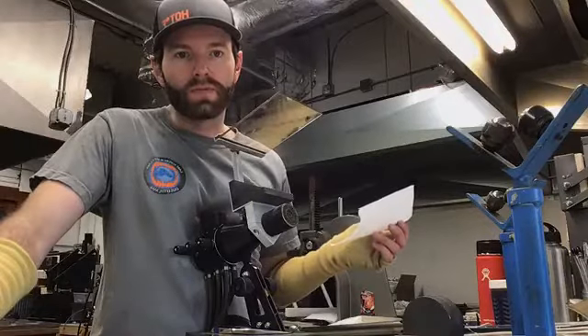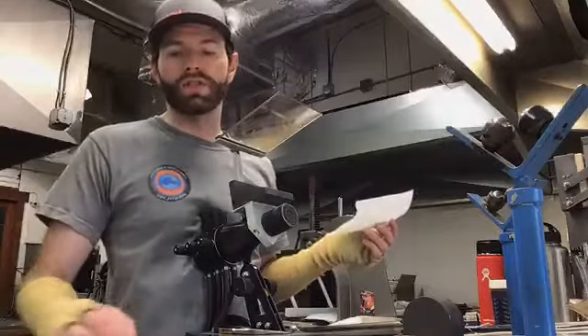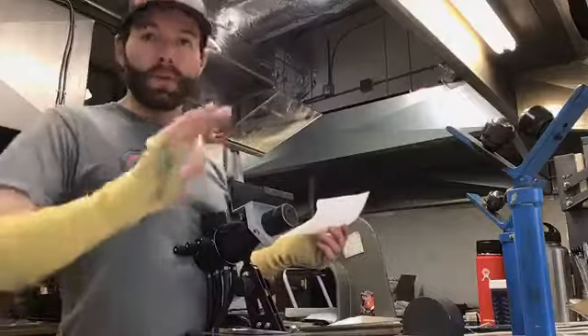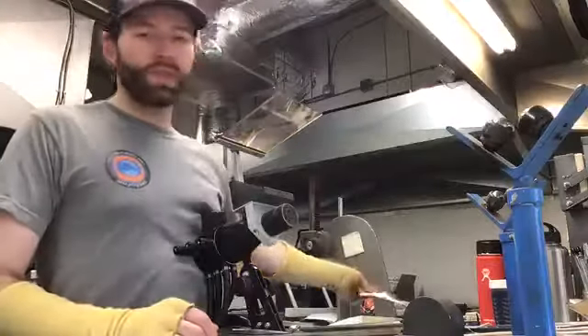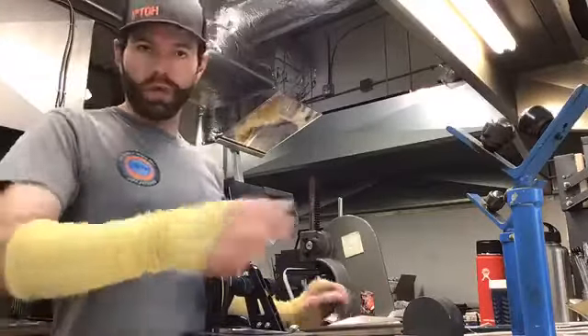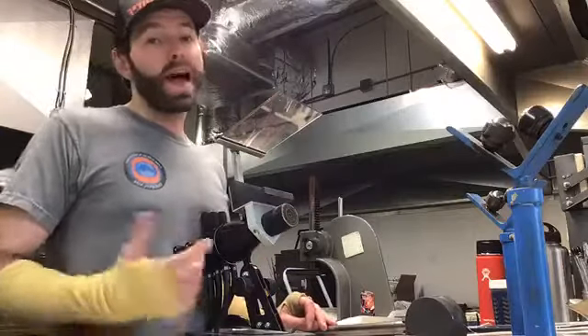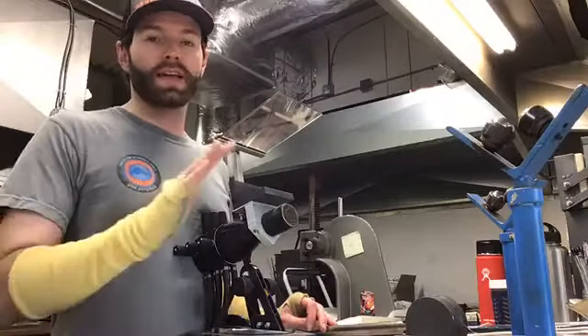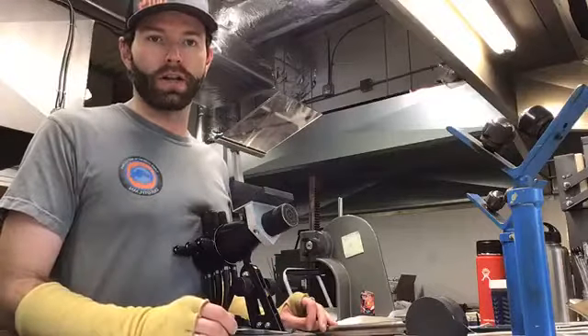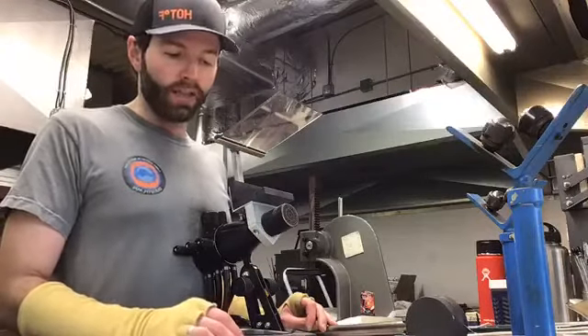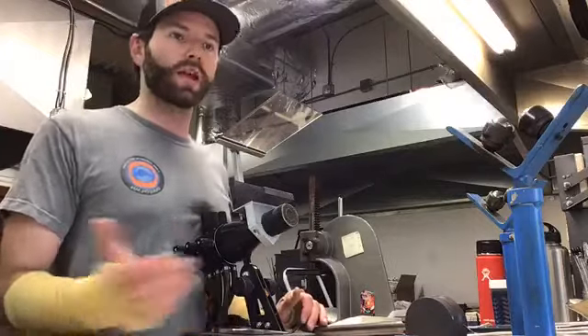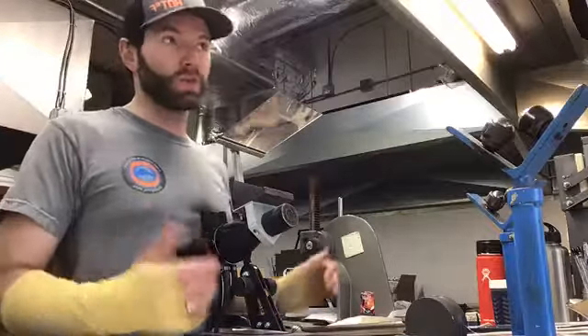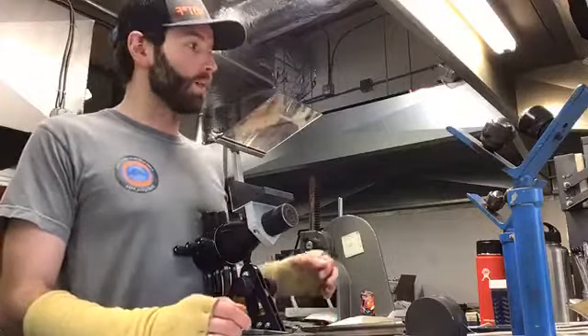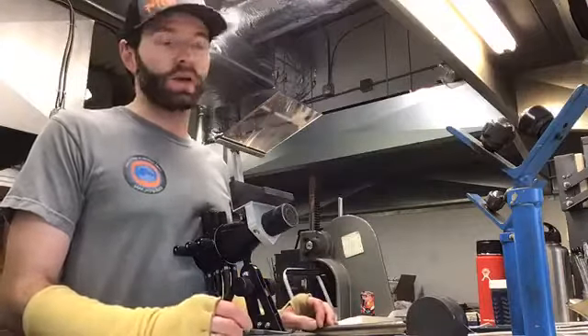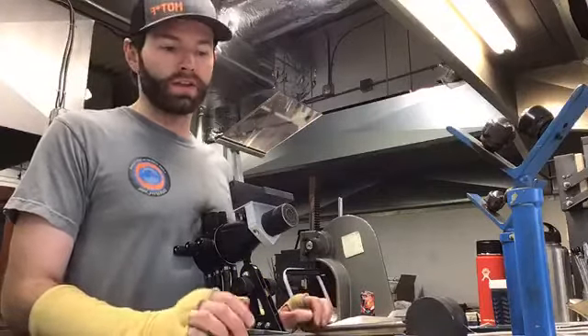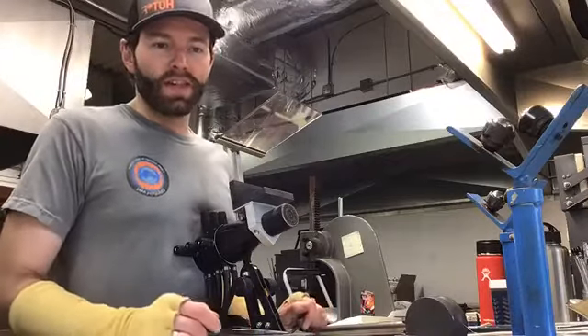Auntie Dante asked, when you first put it in the kiln, what keeps it from flattening a bit? The glass isn't hot enough to change shape at that point. The very bottom where I was polishing with the last point of connection and where that dragon's eye was, that could be a little hot, and so I always make sure that side isn't down or touching the kiln when I put it in there. So good question, but in theory, none of the glass should be hot enough to move when it goes in there, and so it does involve finding that sweet spot. If you put it in there too cold, the heat of the kiln will crack it. If you put it in there too hot, you're going to get a mark. So there's even a science to that.